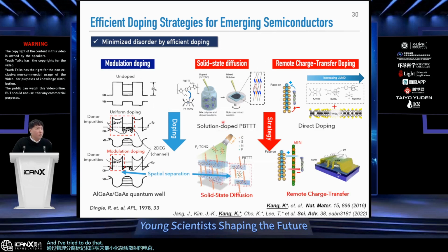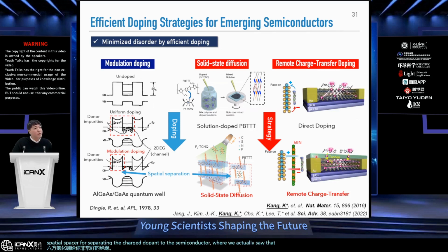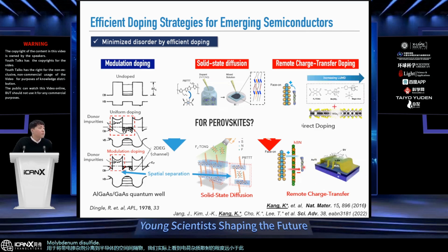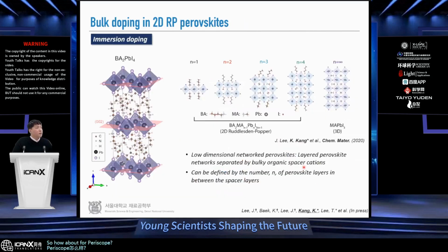And I've tried to do that for organic semiconductors, and there comes in my 2D work, where I thought, okay, this should be able to be done for 2D materials, where the hexagonal boron nitride gives you a very nice insulating spatial spacer for separating the charged dopant from the semiconductor, where we actually saw that the extent of charged impurity scattering was much less for this remotely charge transfer doped molybdenum disulfide channel. So how about for perovskites?